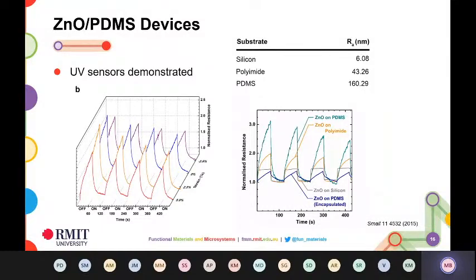I see. Yeah, because I thought it significantly deviates from the commonly used materials like hafnia and alumina and all these. So was there any specific advantage? What I was trying to get at for STO? So we had quite a few papers in 2015-16. We actually had a few patents as well in that space because until then, not many people had done strontium titanate memristors or had a room temperature deposited version of it. And doping gave us quite a lot of advantages. If we wanted to increase the endurance, we could dope it with one particular material. If you wanted to change the kind of switching behavior, we could dope it with another kind of material.